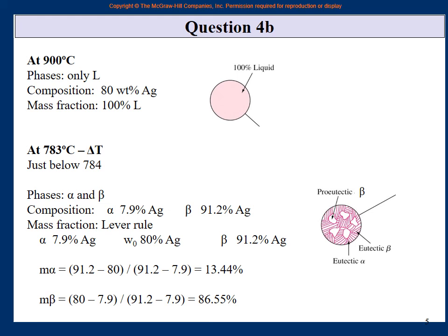And now, if you want to understand, this was critical. We were going on the right hand side. This was 80%. It was not on the left hand side. Left hand side, the liquidus starts alpha, then alpha plus liquid, then alpha plus beta. On the right, it starts beta plus liquid, then alpha plus beta. So the pro-eutectic is the beta here. It is not pro-eutectic alpha. This is very important that it is not on the left hand side of the diagram. This percentage of 80 weight percent original is on the right hand side.